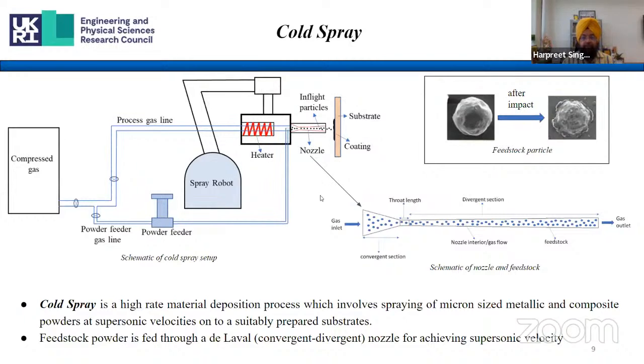And another thing is that we also have a heater here. Some people ask why then we are heating it. So this heating is mainly for thermodynamic reasons, I would say, because we have this expansion at the throat. That means we will have this adiabatic expansion of our gas, which can lower down the temperature of the gas, and it can hamper the critical velocity to be achieved, or velocity of the gas. So that is why we heat the gas here.